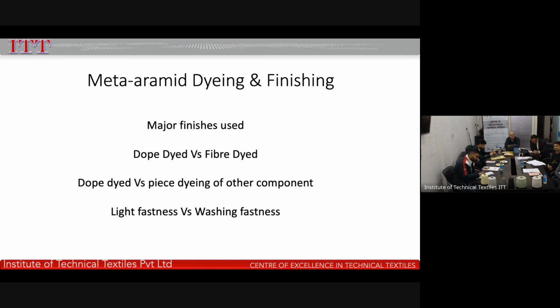Light fastness in the case of dope dyed is to the level of 5, but light fastness in the case of dyed is generally in the range of 3 to 4. Here the dye selection will matter. Washing fastness, you will have to give a really strong wash to remove all the surface dye to get a very good washing fastness.